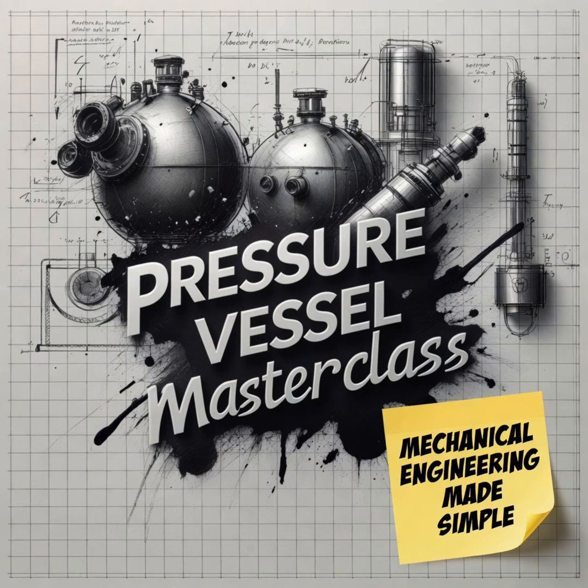So it's literally supposed to crack. To a degree, yes. Furthermore, when the vessel finally shuts down and cools off, the hot face of the refractory experiences irreversible thermal shrinkage. This propagates fine shrinkage cracks through the lining. But here's the critical key to the whole system. When the vessel fires back up and heats up to operating temperature again, that massive thermal expansion on the hot face causes all those shrinkage cracks to close tightly together. Oh, I see. It puts the entire lining under massive compression. The load is perfectly redistributed, as long as the refractory was cured properly initially.